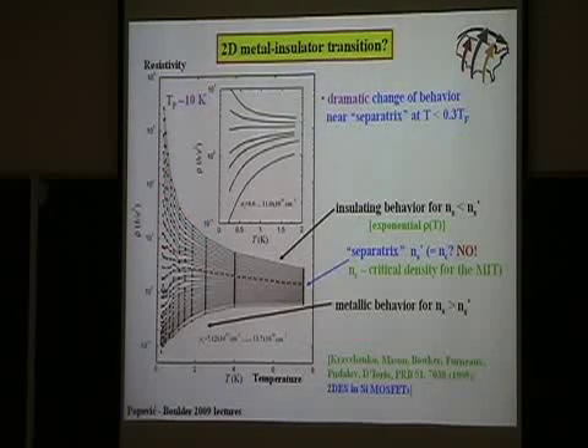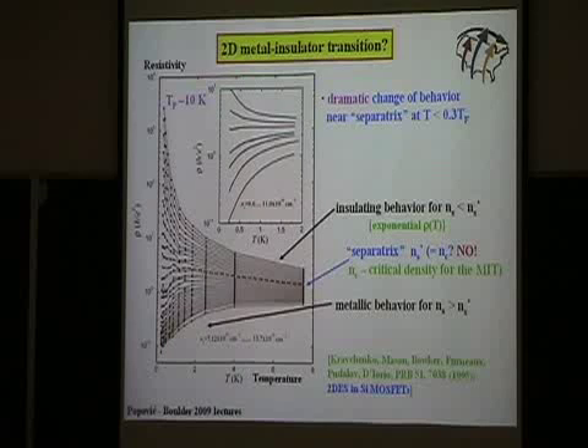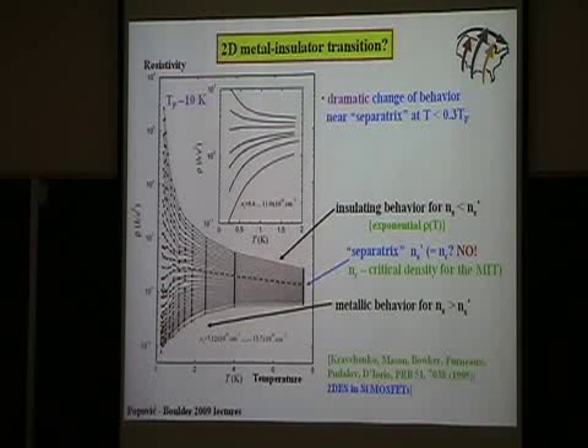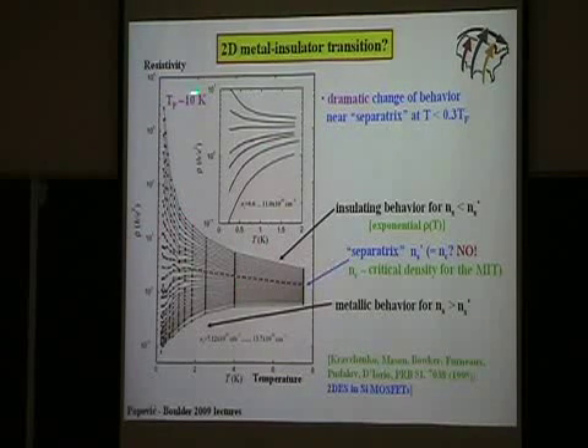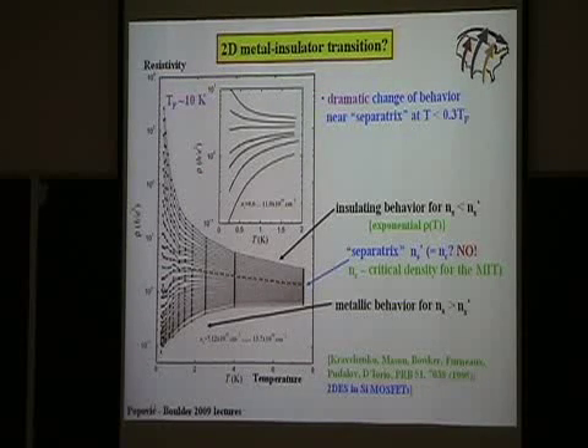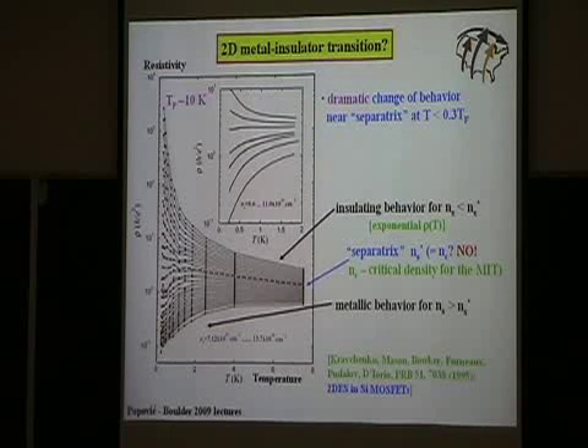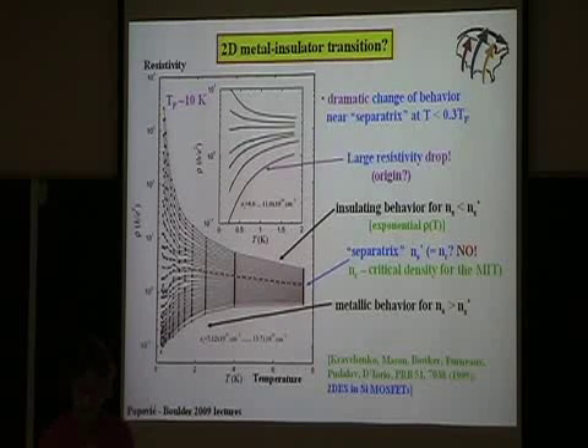The reason to try this is because this is supposed to be a quantum phase transition. So you want to see whether the conductivity exhibits the scaling that I mentioned earlier that is expected in the general case. So this is what these people did. Actually, such measurements have been done many years ago by other people because, as I said, a large number of people studied these systems. However, because of those ideas from the 80s, they did not believe there was eventually a true metal-insulator transition. So Kravchenko and collaborators wanted to provide some evidence for the existence of a true metal-insulator transition, and they decided to attempt scaling.